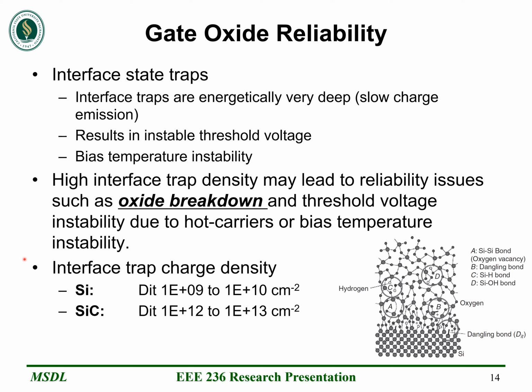As a frame of reference, here is the interface trap density for silicon versus silicon carbide. You can see the interface trap density for silicon is about 1e9 or 1e10 per square centimeter. And for silicon carbide, it's about 1e12 to 1e13 per square centimeter. So there's a very dramatic difference in interface trap density moving from silicon to silicon carbide.